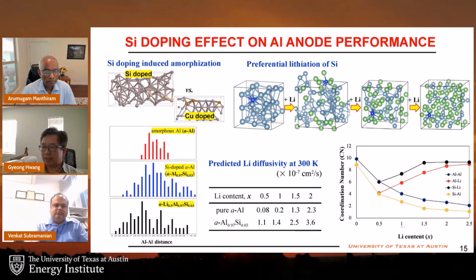Then we look at the lithiation behavior of silicon-doped aluminum. In the top right figure, the blue, the gray, and the green balls represent silicon, aluminum, and the lithium atoms, respectively. The results clearly show the preferential interaction of lithium with the silicon over aluminum. So in addition, the lithium diffusivity tends to be enhanced when the aluminum matrix is doped with silicon, as presented in the bottom middle table.